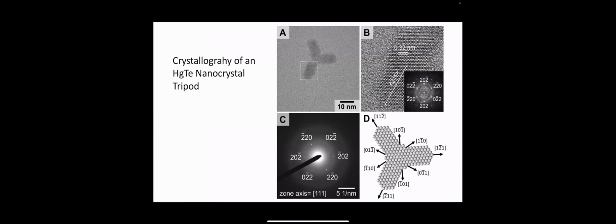We've been looking at what are the growth directions of those arms. So the arms can grow in the 1-1-1 direction quite a bit. Also the 2-1-1 direction. Depends on the synthesis, the size of the wires. So a little bit larger arms tend to grow in the 2-1-1 direction. Thinner arms tend to grow in 1-1-1, and every so often we'll see an odd 1-1-0 growth. But usually it's 1-1-1 for very thin arms and 2-1-1 for a little thicker.